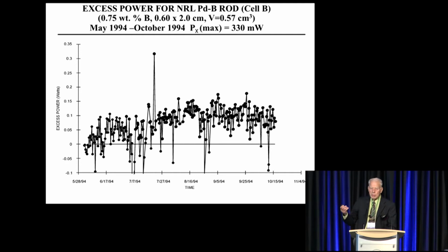Some days I would ramp the current up, maybe from 500 milliamps up to almost 1 amp. Well, I found with palladium-boron, when you make a sudden change in current, the excess power often goes away. And not only that, some terms I was leaving out, like the heat carried away by the gases and the work done by the gases. We didn't even know about work. Nobody was using the work term at that time. But those would add to the excess power and bring it up closer to zero. And I should say about calorimetry, almost every time you see things below zero, that's likely a calorimetric error. Very seldom do you see any endothermic process. So just look, see how many times the data shows values below 0, and you can consider that probably the error range.